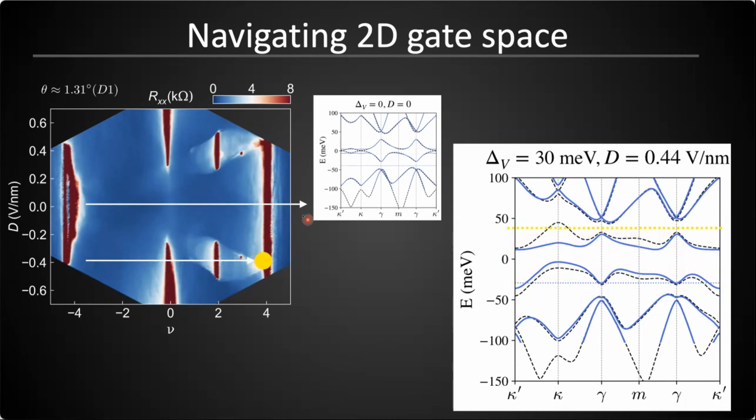half filled, and then fully filled. And so you can see this state right here when the first conduction band was half filled. That's a correlated insulator state. It's the same place that you would expect a Mott insulator, but the origin of this resistive state seems to be broken symmetries, not a Mott insulator. So we'll talk about what that means in a few slides. Okay, and so here, again, that's that half-filled state when the Fermi energy is right in the middle of this flat band.